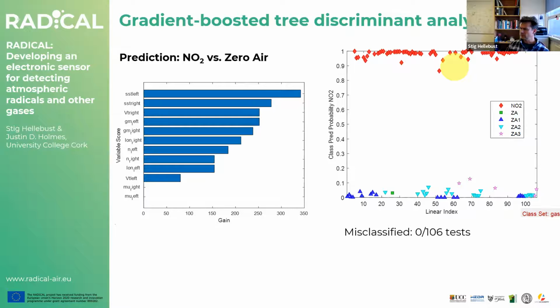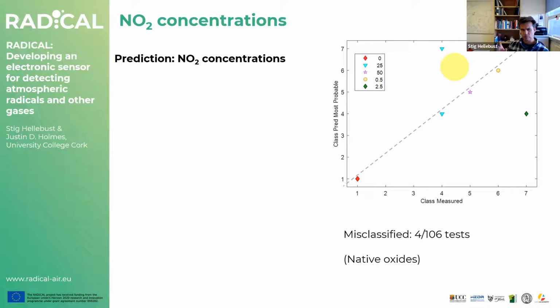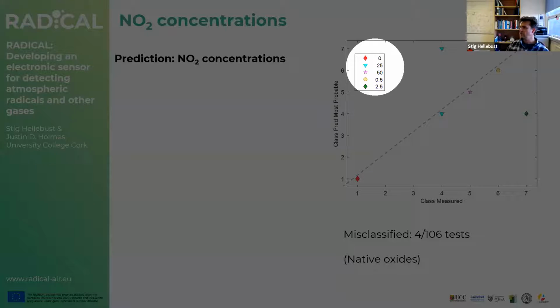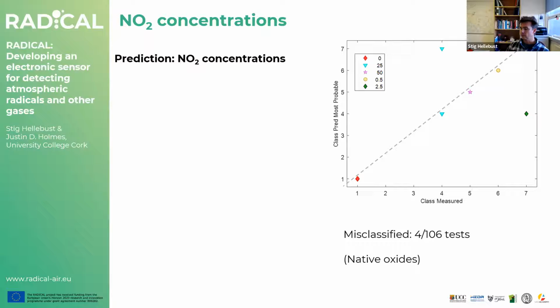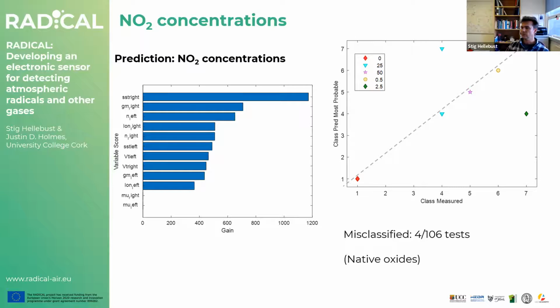But this went well, so we can be a little bit more ambitious and look at actual NO2 concentrations, same model, and it's the same result really. If you look at the concentrations that we actually tried and the concentrations that are predicted, there are only 4 out of 106 tests that were misclassified. And those were all the native oxides. So I think this is promising. Of course, we still have to try it with radicals, but again, it's instructive to look at, to understand what is actually happening in terms of the chemistry and the interaction. It's instructive to look at the features that seem to be important in this prediction.